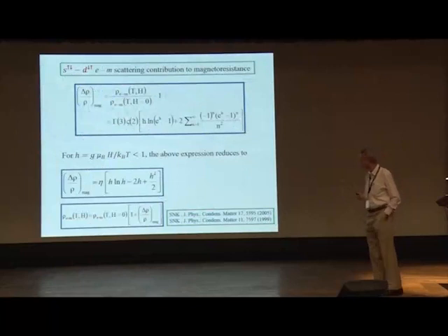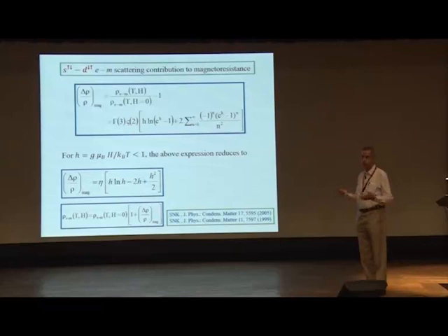Now I go to the magnetoresistance. Here, as we know, other contributions, for example electron-phonon, you don't expect to get reflected in magnetoresistance. It will be only the electron-magnon part. And out of that electron-magnon scattering, it is basically the so-called spin flip interband SD scattering which actually gives rise to the magnetoresistance.